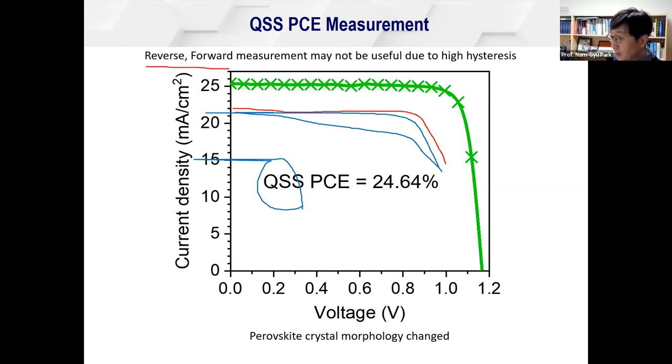However, nevertheless, we should decrease further the solubility product of PbI2. That is a very good method in heavy metal treatment, in academia or industry. Chemically, we can utilize phosphate. Phosphate is well known for its very strong interaction with Pb2+. For instance, lead phosphate has a solubility product of about 10 to the minus 32. It's almost non-soluble. So this is good, and we are working on introducing some phosphate groups into the perovskite layer.